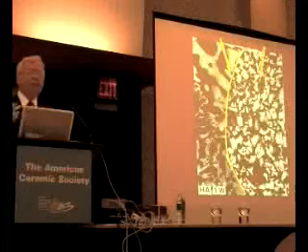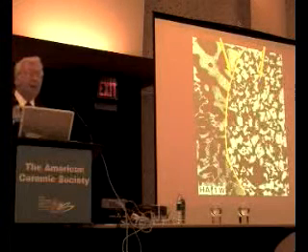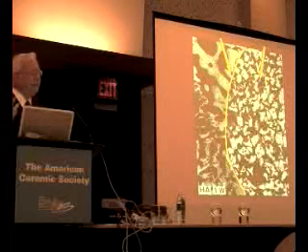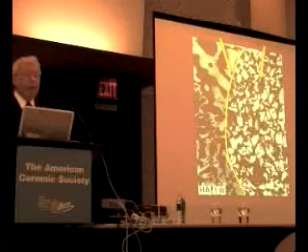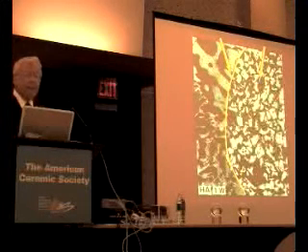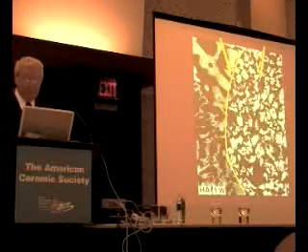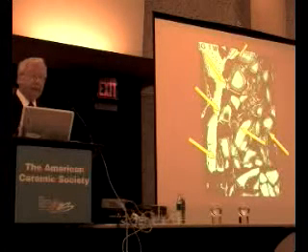Comparative studies were done of all synthetic materials. This gives one example of the huge difference between the Class B bioactive materials, where bone will grow only by osteoconduction, versus the Class A bioactive 45S5 bioglass. After one week with a synthetic hydroxyapatite, the yellow line shows very little if any bone penetrating inside the defect. In contrast, with the Class A 45S5 bioglass, within one week there are bridges between particles penetrating at least halfway into the defect, creating new bone and showing rapid colonization on the surface of the particles.